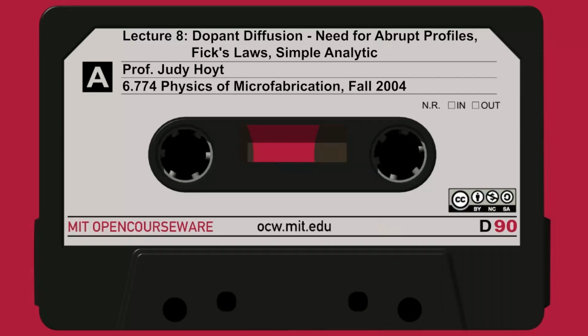Boron, again the only really available p-type dopant, is relatively fast, with a diffusion coefficient that can be a factor of 10, 20, or 30 higher than the slower diffusers such as arsenic or antimony. So this gives you a rough idea that when we talk about dopant diffusion, what we're going to have to worry about a little bit more are the fast diffusers, say boron.